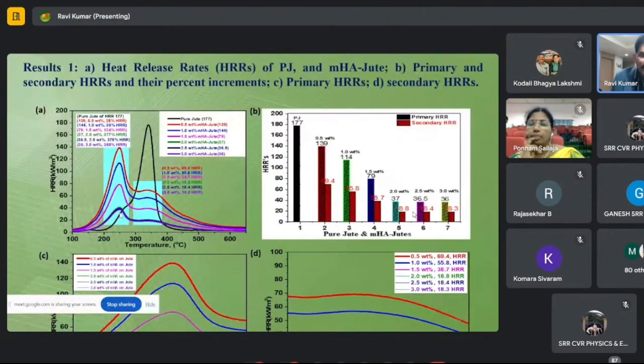This is the highest heat release rate reduction and it shows a very strong HRR, and the temperature you can find here at around 250. It means that when the temperature increases, automatically the resistance also increases, using different weight percents from 0.5 to 3 weight percent. But we concluded only 1, 2 and 3 because we wanted to commercialize. We cannot supply all combinations. So we standardized only 3 out of 6, that is pure jute along with 1 weight percent, 2 weight percent and 3 weight percent.